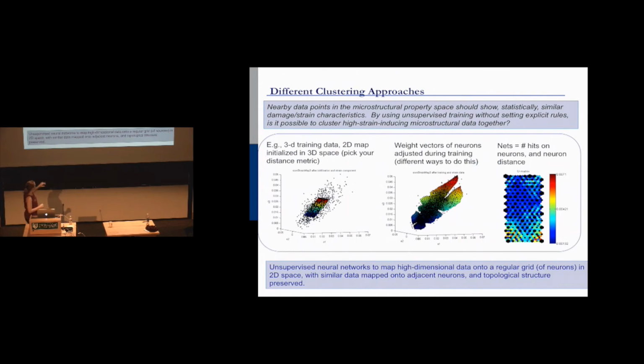And then the basic tenet being that when you have nearby data points in the microstructural space, so you take your microstructural 100 to 200 variables, you dump them into 200-variable dimensional space, and you try to cluster them in that space. And we do that by neural net. So you change the weighting, and you say, okay, these kind of belong together, these kind of belong together. You know, Schmid factor is super important, so these are clustered, these are clustered.